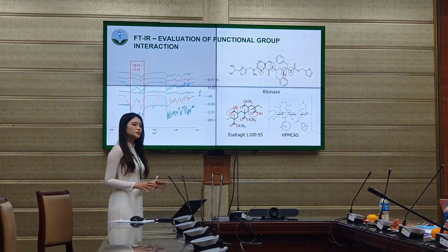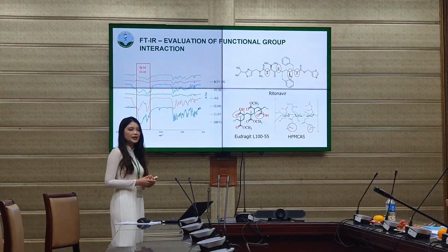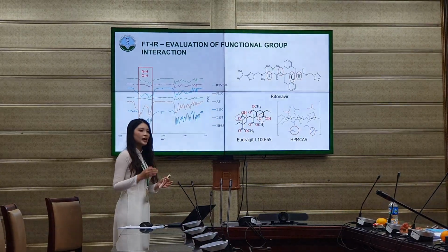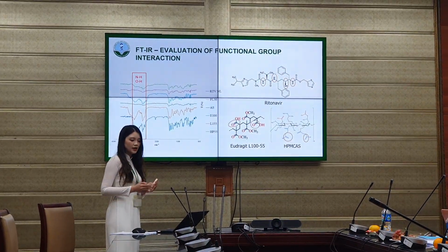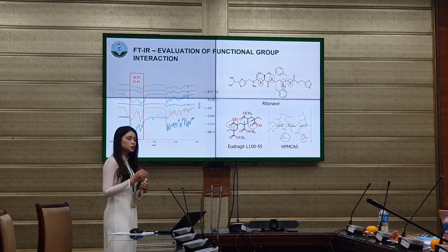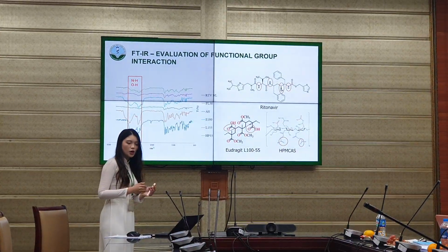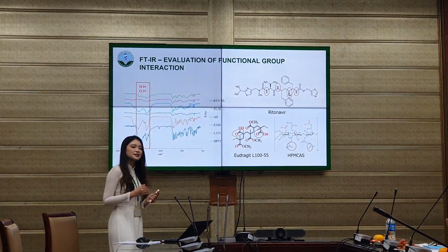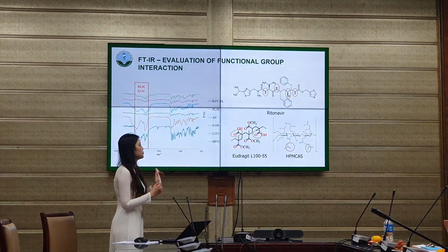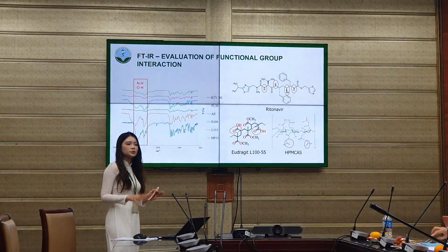So the molecular interaction is very important in solid dispersion, especially the amorphous solid dispersion. It helps improve the physical stability as well as the dissolution behavior, because molecular interactions reduce the mobility of drug molecules, and upon polymer dissolution, the drug is simultaneously released into the medium through a co-dissolution mechanism.